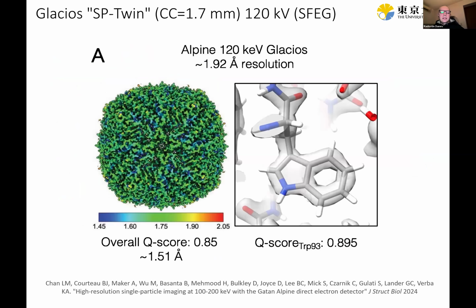Now, there are also recent results at 100 keV by Gabe Lander and Clement Verba. They did tests of the Gatan Alpine detector, which is also designed to operate at the lower voltages, 100 and 200 keV. And they got very similar resolution from their dataset as well. So these two datasets are very close to each other, and they show that in principle, it's possible to get sub-2 angstrom resolution results at 100 keV, but it's challenging. My personal experience is that it's more challenging than getting them on the 200 or 300 keV microscopes.